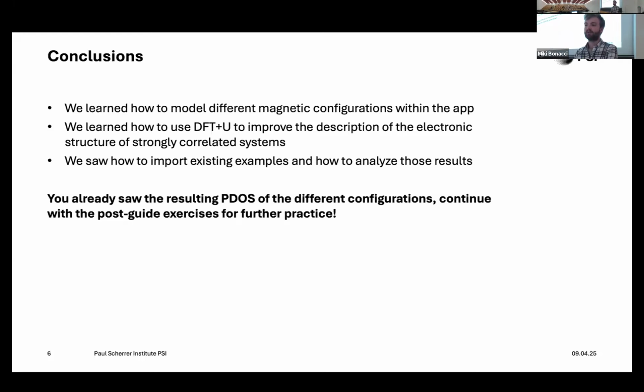Sometimes people also determine it empirically, so to say: if you're interested in a band gap, you tune the U value so that you reproduce the band gap. But in this way, it's not really ensured that this also works for, I don't know, thermodynamic stability, for example. So, yeah. Thank you. Sure. Anything else?